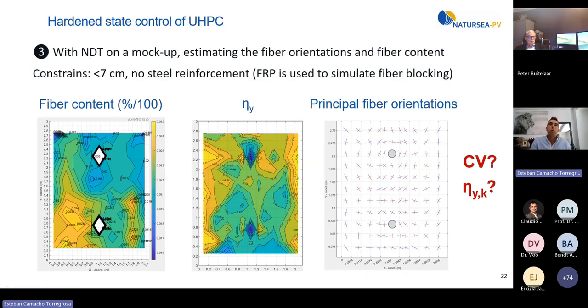There are non-destructive tools, also based on inductance, that can be used to estimate fiber orientation and fiber content in elements that are thinner than 7 centimeters and without steel reinforcement. In case we want to understand how steel reinforcement is going to affect our fiber orientation, we can replace the steel reinforcement by glass fiber reinforced polymers or any other kind of rebar which is not metallic. Then we will see how the fibers are blocked, how they are oriented around the reinforcement, without affecting this device. Here you see the results of doing this determination in a slab of 2.7 by 2 meters. You can see on the left side how accurate the determination of the fiber content can be, which here varies between 1.8% and 2.4%. So fibers are not distributed perfectly.